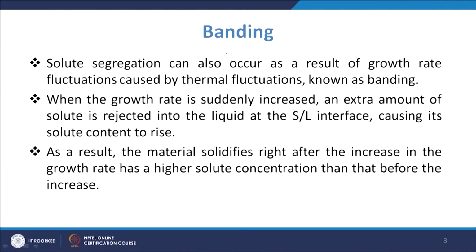This solute segregation can also occur as a result of growth rate fluctuations caused by thermal fluctuations, and in that case it is known as banding, because we have seen in that expression where we have G by R on one side, and on the other side delta T upon DL, R is the growth rate, and that becomes important even for the solute segregation.